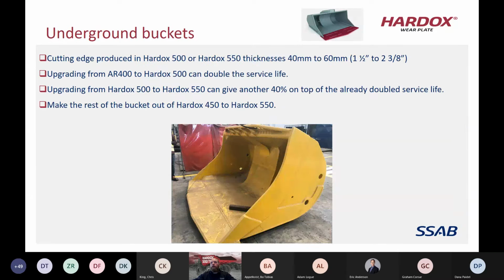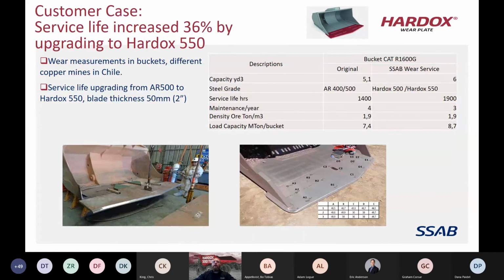So for underground buckets, the cutting edge can be Hardox 500 or Hardox 550, in varying thicknesses. It really just depends on your application and what you're looking to achieve. When upgrading from, say, an AR 400 to Hardox 500, you can many times see double the service life. And this is a customer case where they increased the service life by 36%. They upgraded to a Hardox 550. A lot of it was AR 400 and 500, and they did a direct correlation to Hardox 500 and Hardox 550 and saw a 36% increase in service life.